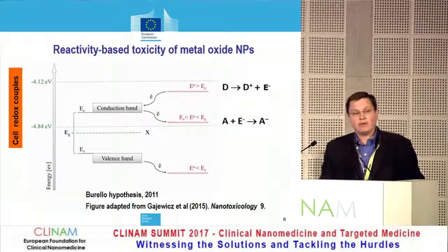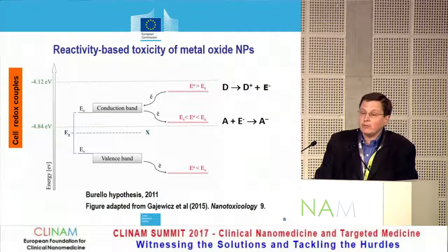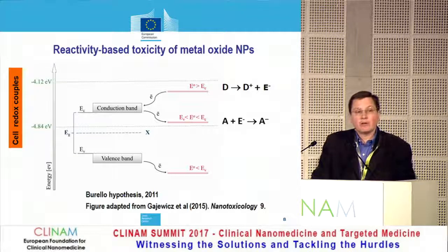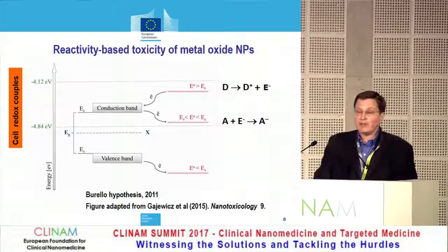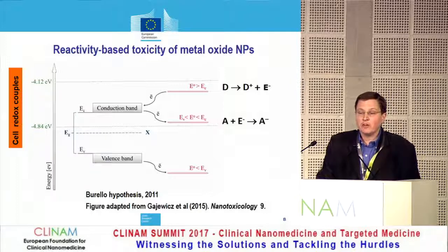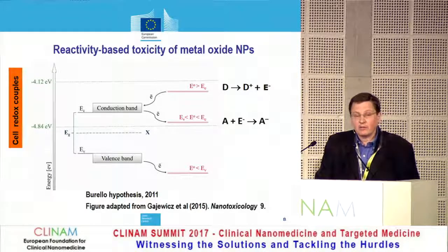Now, this works very well for molecules and long molecules such as carbon nanotubes, carbon nanoneedles, but it doesn't really work for chemicals in a crystalline form, because here, of course, the close proximity of the many atoms means that the molecular orbital energies tend to overlap and they split, and what you actually get is a valence band and a conduction band, and these are separated by an energy gap.